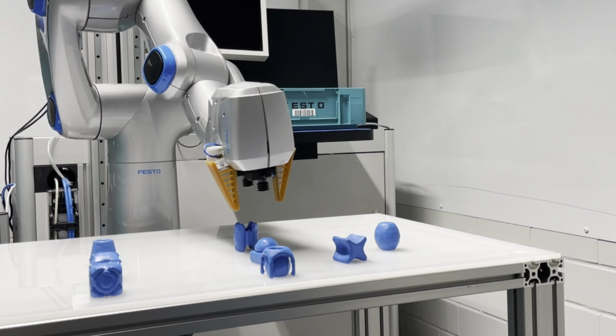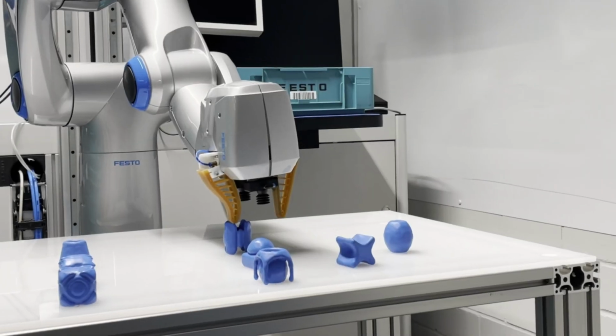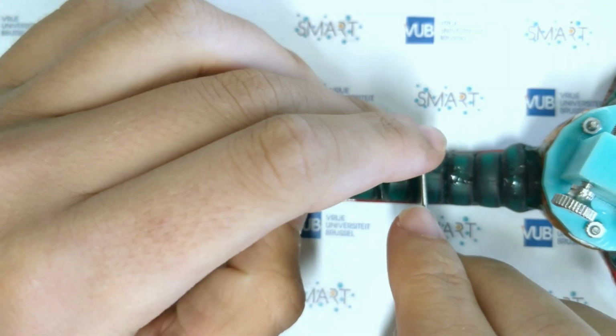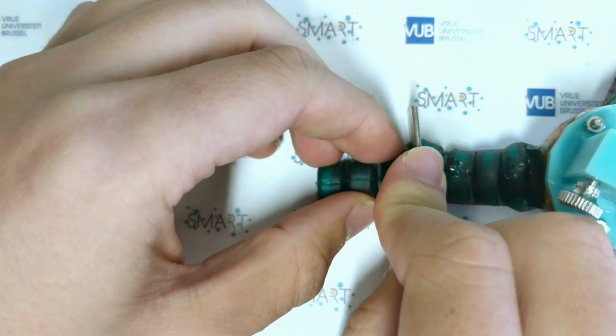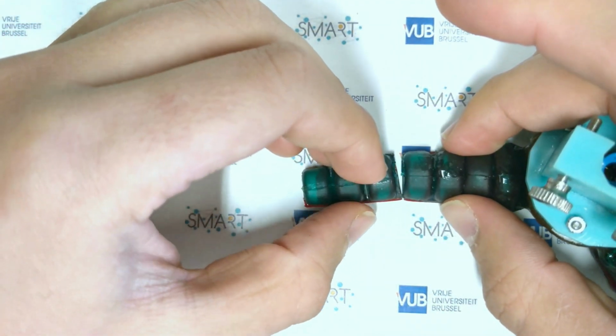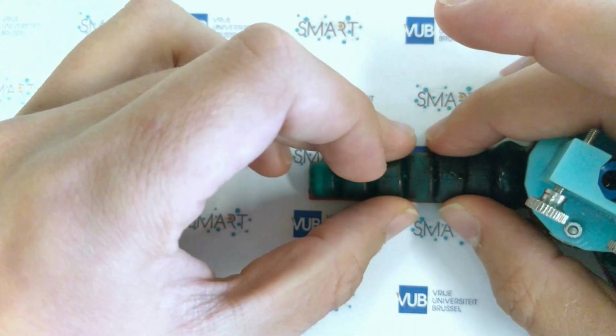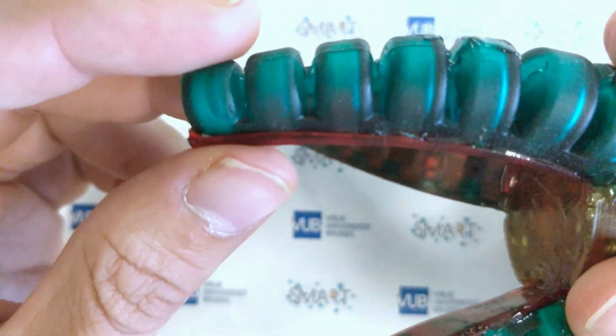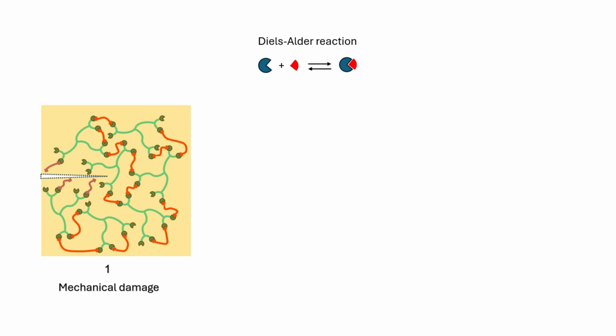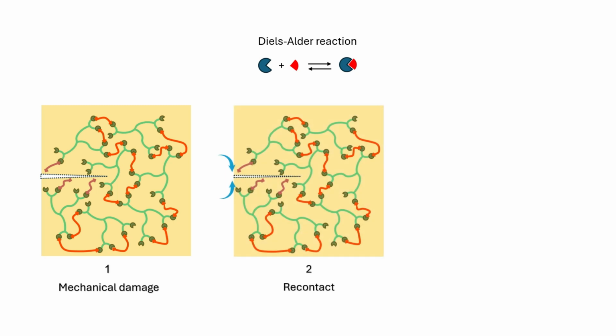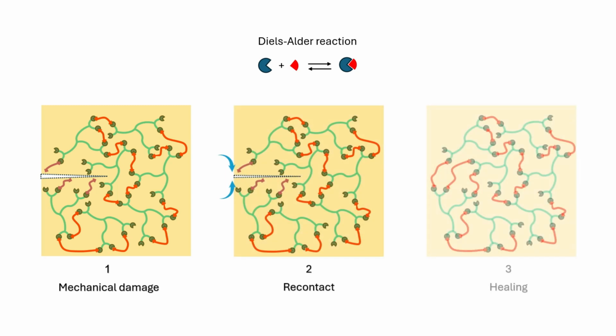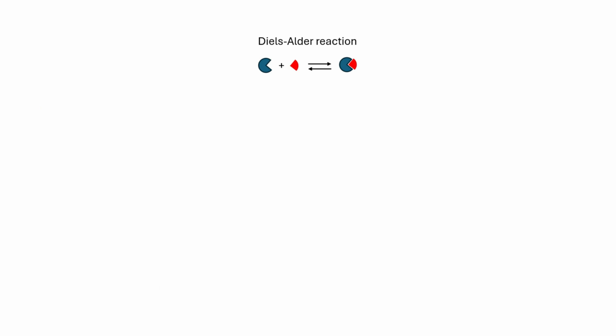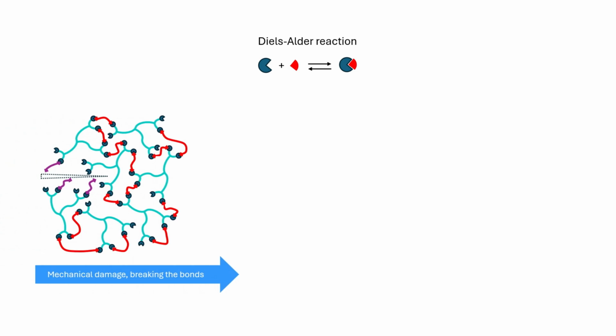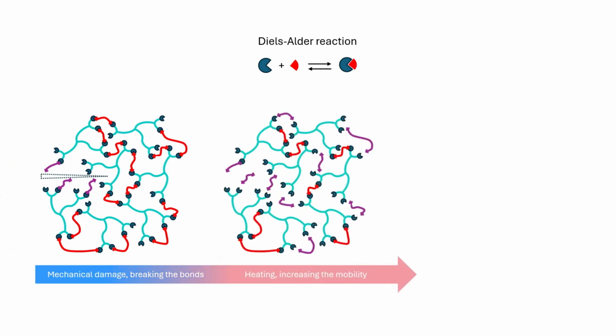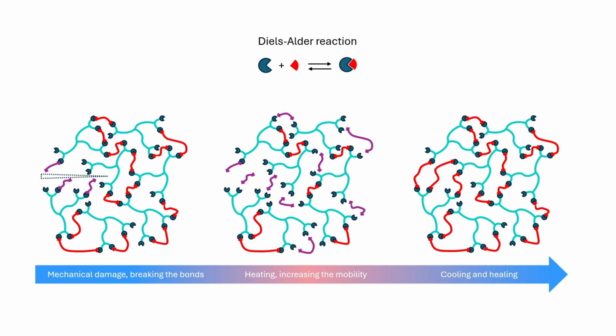While soft materials can handle shocks well, they can be damaged by sharp objects or stretched too far, just like biological soft tissues. The solution again lies in nature. In collaboration with our polymer group, we have developed self-healing materials based on Diels-Alder reaction. These are dynamic covalent bonds that can break upon mechanical damage. But upon recontact, and due to their reversible nature, they can reform and create new bonds. In many cases, this process is stimulated by a heat-cool cycle. Raising the temperature breaks more bonds and increases the network mobility. Cooling allows them to reform, enabling healing across the damage.